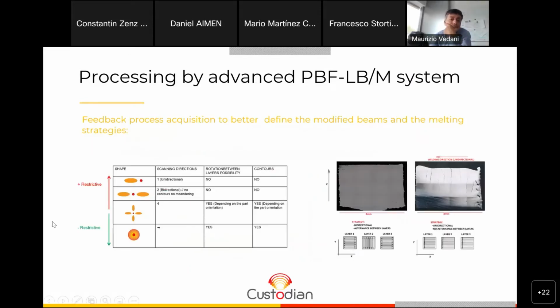And as mentioned before, prior to the beam shaper definition, some tests were conducted in order to obtain some process feedback and some information to support the simulation model, right? So as we are modifying the shape, different approaches were initially proposed, as you can see in the table. However, as you may know, the powder bed fusion laser beam melting process works very randomly, producing tracks in multiple directions, moving back and forth continuously. We have to bear in mind that asymmetrical shapes might affect the samples negatively because we cannot rotate the shape with the MPLC. So several tests were carried out under different scanning conditions, as you can see on the right side of the slide.